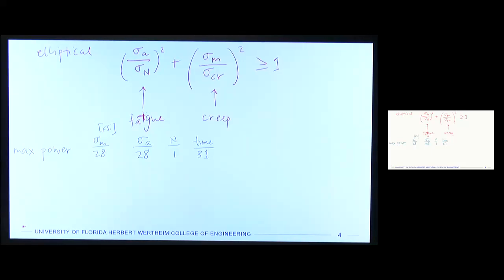have 4 stress regimes, and we have also 4 power settings. And those are not exactly equivalent. So when we talk about fatigue, we talk about these reversed cycles. Well, those reverse cycles happen between 2 of these power settings. So we don't have a way of exactly matching in time the fatigue component of it and the creep, right? Because fatigue is n, it's number of cycles up and down. Creep is time, right? And so because I can't specifically put those together, what I'm going to do is I'm